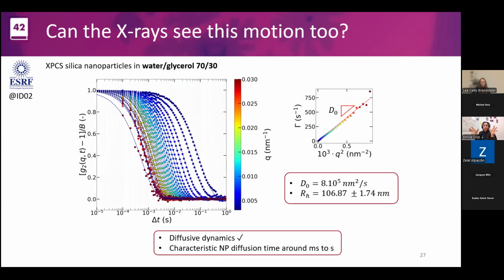So we go and see with X-rays, which can only see the particles, no matter how much we concentrate the space with microgel. And then what we see is that first we do this simple experiment. So we do the X-ray photon correlation spectroscopy. So this time, instead of light, our beam is the X-rays. And again, we get the correlation time that we expected. We compute our diffusion coefficient.